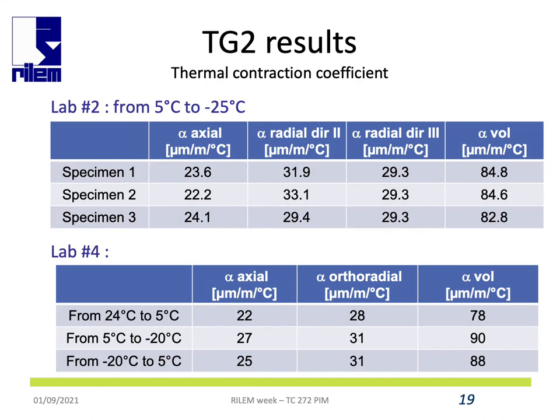Moreover, these tables highlight the effect of the initial temperature on the thermal contraction coefficient, showing that it is necessary to control the temperature field inside the sample if we want to have reproducible measurement.